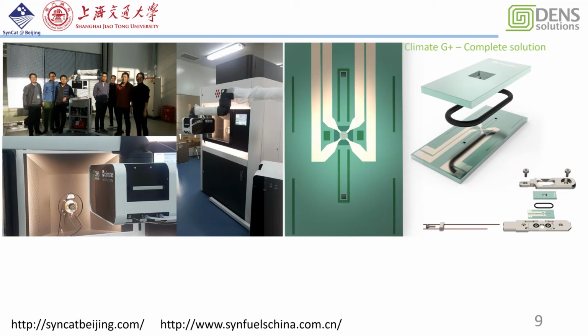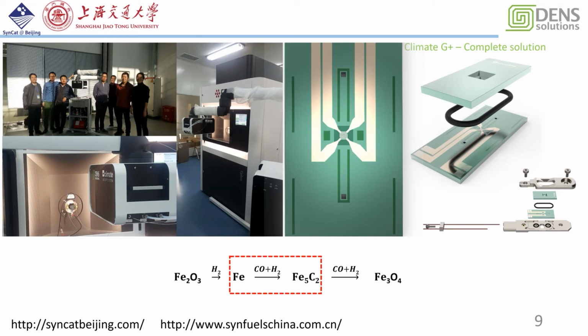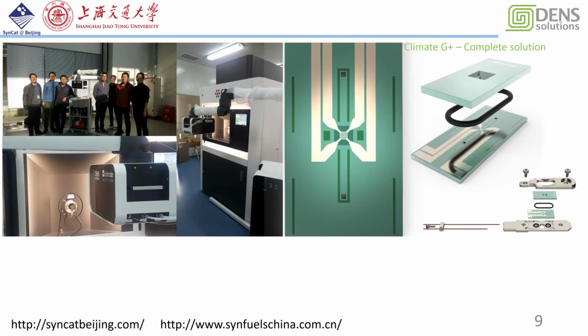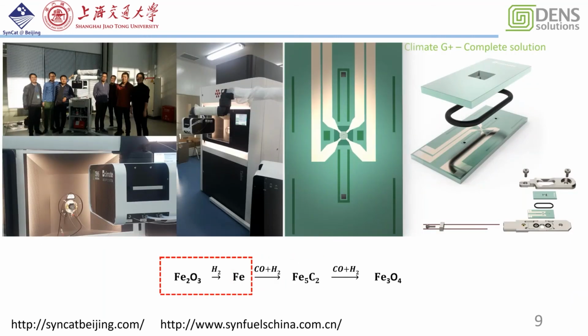And this is just to show how the instrument works. Using the instrument, we can directly introduce gas inside the TEM and raise the temperature from room temperature to almost 1,000 degrees, and manipulate the hydrogen pressure from several millibar to 1 atmosphere. So we observe how the reaction happens from iron oxide to the active catalyst iron carbide, and also the deactivation to magnetite. The most successful story is that we use this technique to carburize iron to iron carbide. But this part of the work I will introduce with just several slides of the PPT. Mainly, I will talk about this story: iron oxide to iron.